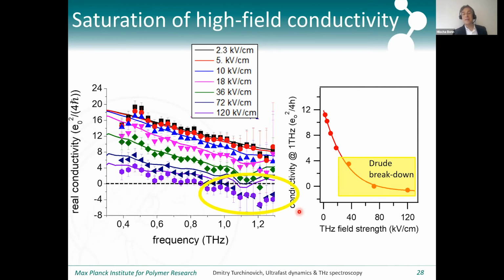So now there's one thing that I'd like to point out here, which will be interesting. We did not at all understand it at the time, but you can see here that at high frequency, it looks like we're having a negative real conductivity, which actually corresponds to there being gain in the system. So there's more terahertz intensity coming out of the sample than going in. And I will show you that this is actually real later. But at the time, we just didn't understand it. So we thought we must be making some systematic mistake.